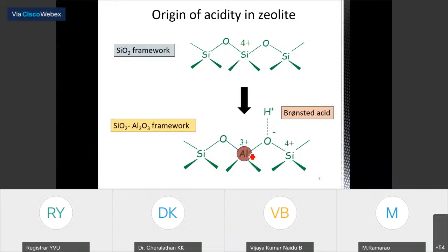And why are these zeolites acidic? What is the origin of the acidity of these zeolites? That's what I'm going to explain in this slide. If you think about only the silica framework, it is made up of only silicon and oxygen. You won't have any acidity at all. It is a neutral framework. But when you incorporate aluminum into this framework, as shown here, what will happen? There will be an extra negative charge. This extra negative charge should be compensated. If you compensate this extra negative charge with a proton, then the solid will act as a Brønsted acid.